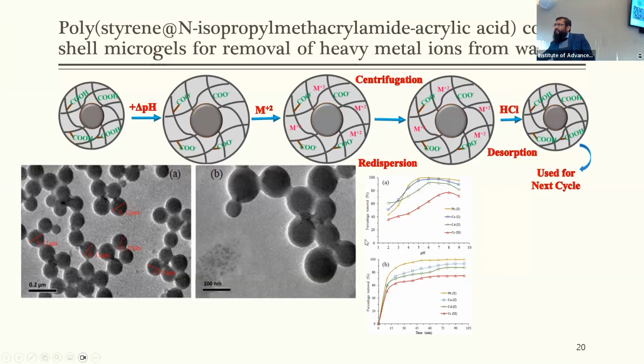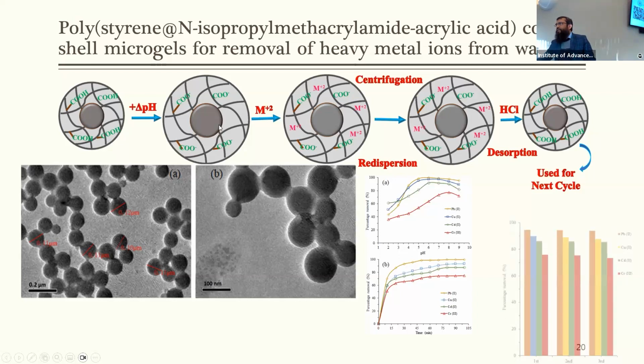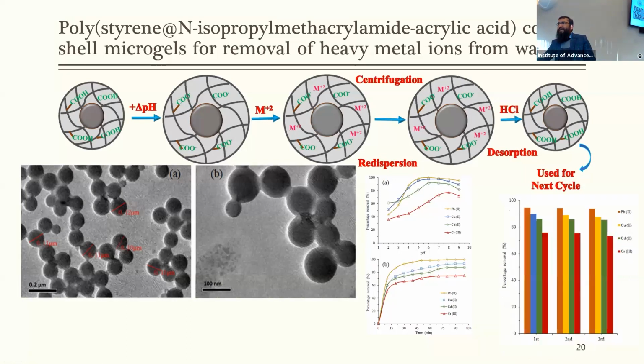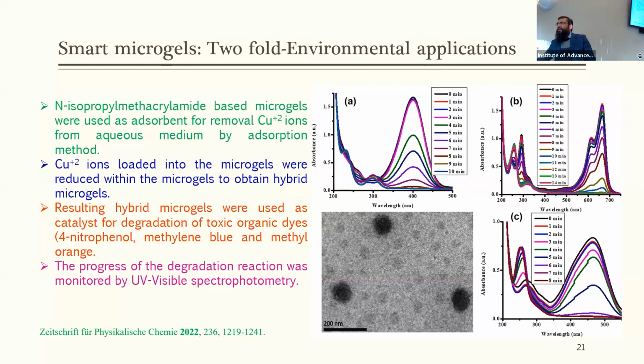We measure the percentage removal of different metal ions using these microgel particles as an adsorbent at different values of pH and contact time. It was observed that the percentage removal can be increased by increasing the pH of the medium, which may be attributed to the conversion of uncharged core shell microgel particles to negatively charged microgel particles. And the system was found recyclable with a maintained removal efficiency.